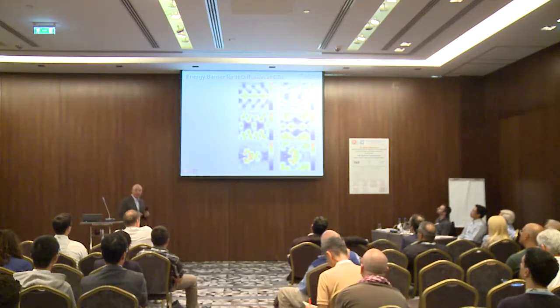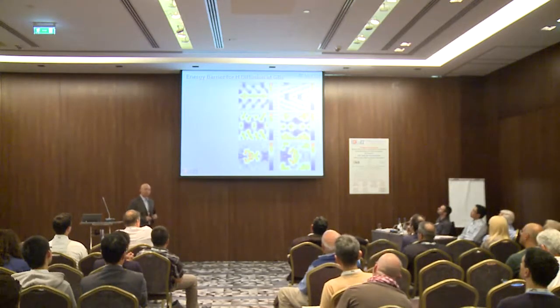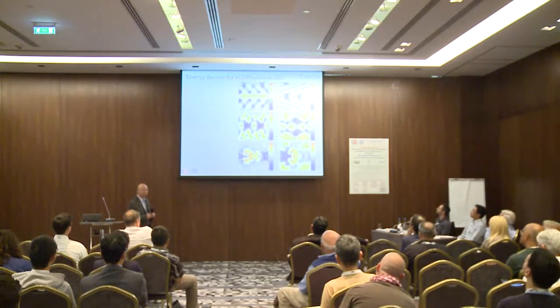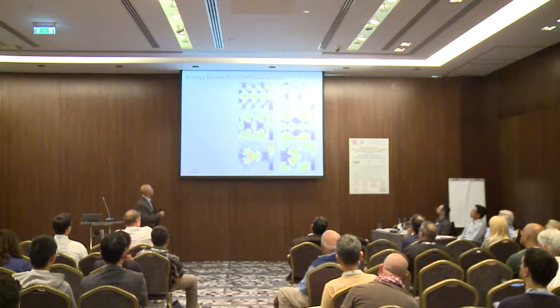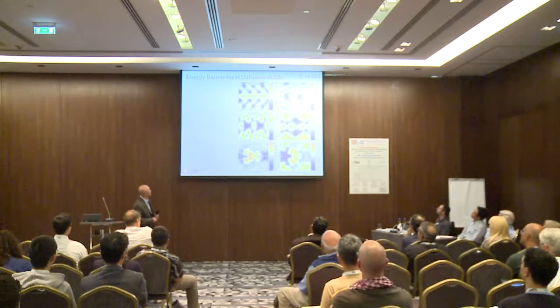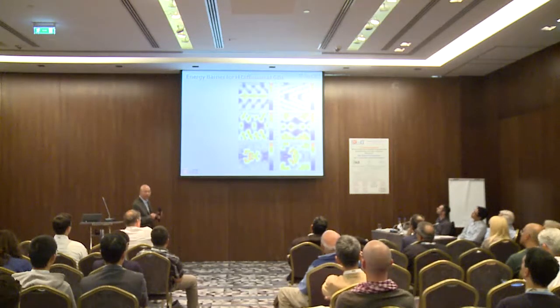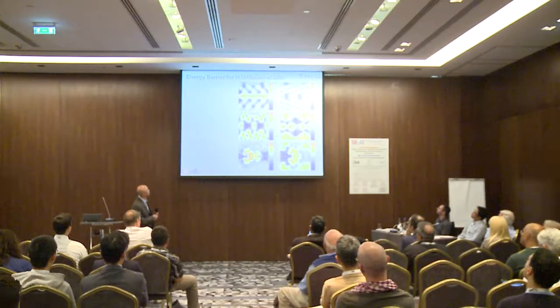Then we can analyze the diffusion barriers for hydrogens along the grain boundary. Of course, it's not just limited to grain boundary. We can then create those maps as illustrated here. So this is basically the contour maps for hydrogen diffusion throughout the lattice.